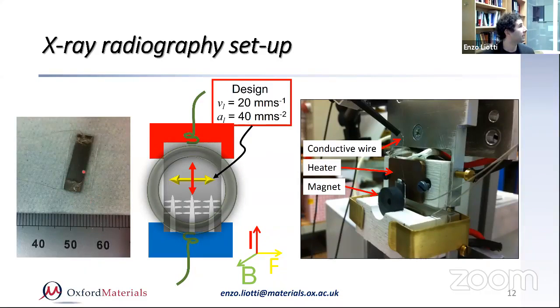This is a detailed image of the sample. You can see the two wires here on the left, and the sample is covered by a coating. Normally it's boron nitride spray powder, just to avoid contact with the silica of the quartz, which would basically dissolve the cell.